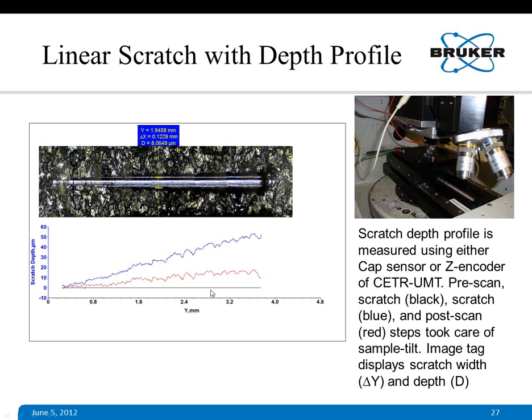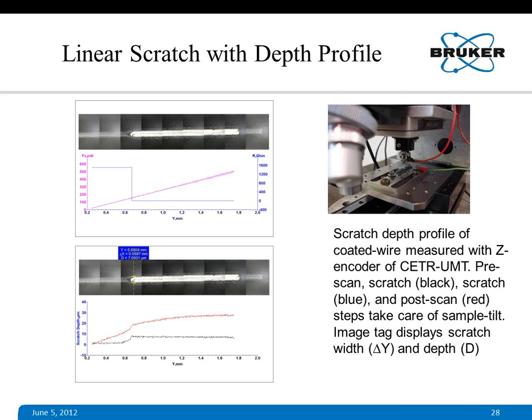On that particular specimen, we also did pre-scan, scratch, and post-scan measurements. Our software allows us to do adjustments, like tilt corrections based on the pre-scan measurements, and those corrections are applied to both scratch and post-scan to have correct values of depth or scratch profile during scratching as well as after scratching. This is done automatically during the scratch test with the procedure of pre-scan, scratch, and post-scan. Here is another example of pre-scan, scratch, and post-scan using a tungsten carbide blade.